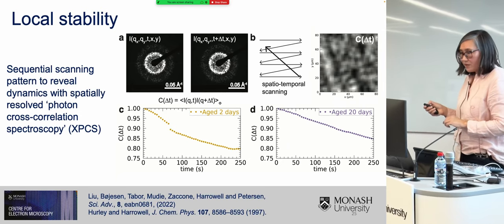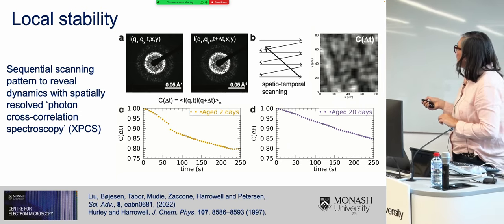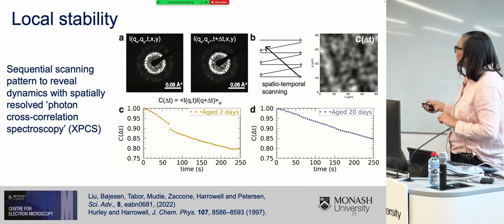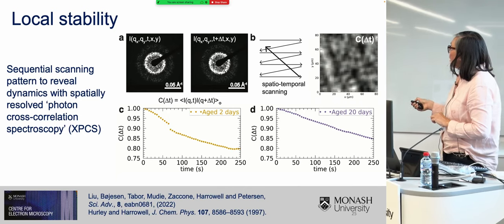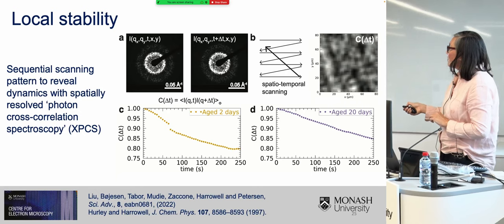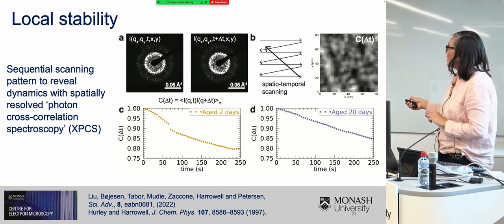So here's how I looked at the local stability. I did a spatio-temporal scanning strategy where I scanned an area and then went back to the beginning. And so I obtained a diffraction pattern from the same area at different points in time. And I calculated this local time correlation coefficient.